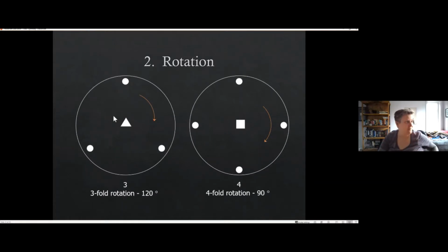Three-fold rotation, the same thing. If we start with this point here, say it's a silicon, and we have a three-fold rotation, we're going to go 120 degrees, produce another silicon right there, another 120 degrees, produce another silicon, and back to where it started, which is the same silicon that we started with. So you wind up with 3 silicons, basically because there's a three-fold rotation there, okay? Same thing with 4-fold rotation, 1, 2, 3, 4, 90 degrees in between them. You can see they're all on the same plane. They haven't rotated down into the different hemispheres. They're staying on that same flat plane.